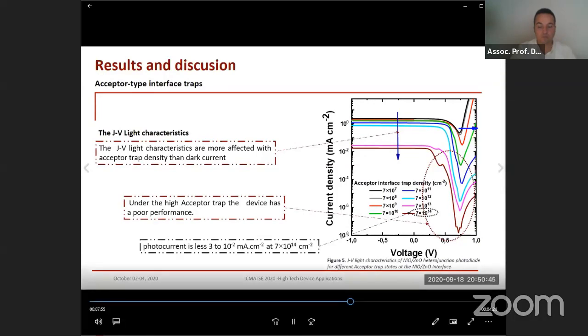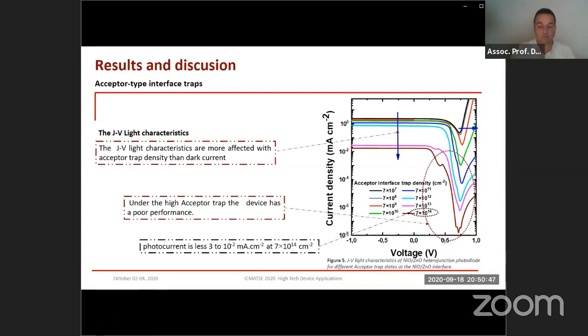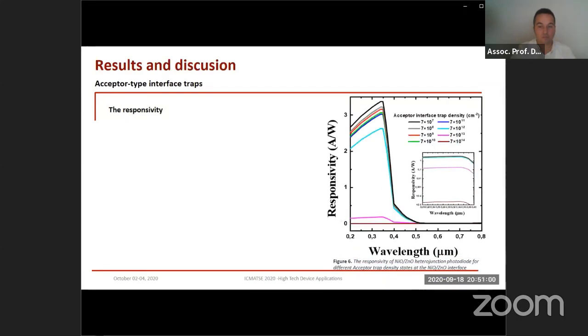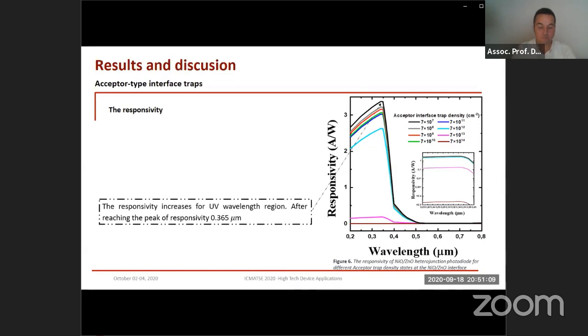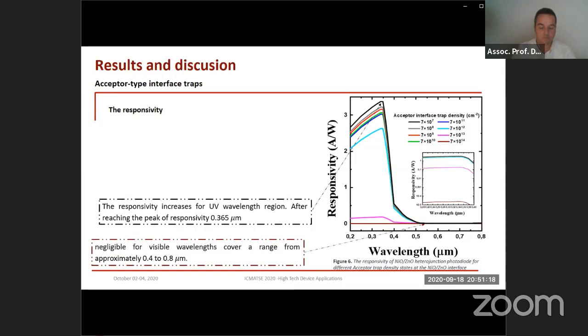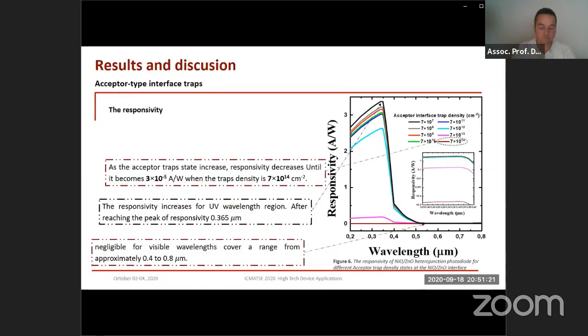This leads me to my next point: the influence of acceptor states on the responsivity. The responsivity of a photodiode is the electrical current divided by the incident optical power. By looking at this figure, the device detects in the UV region, with negligible response in the visible region. The most important note is that higher acceptor trap densities give weak responsivity, until the value reaches 30 micro-amps per watt.